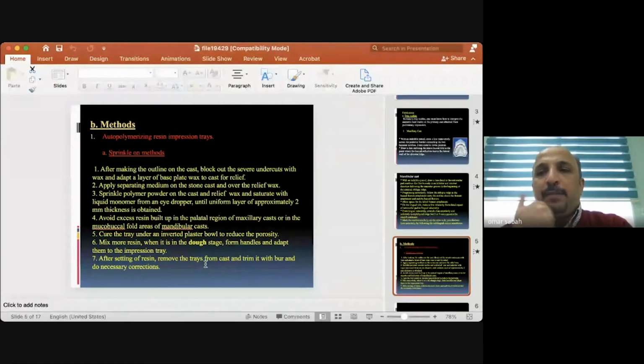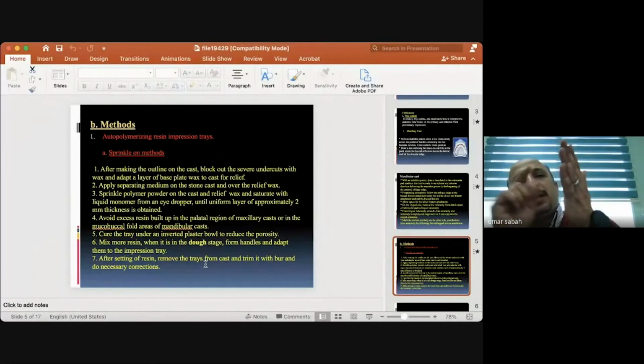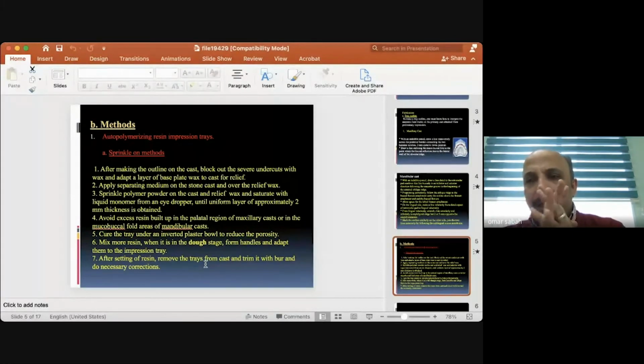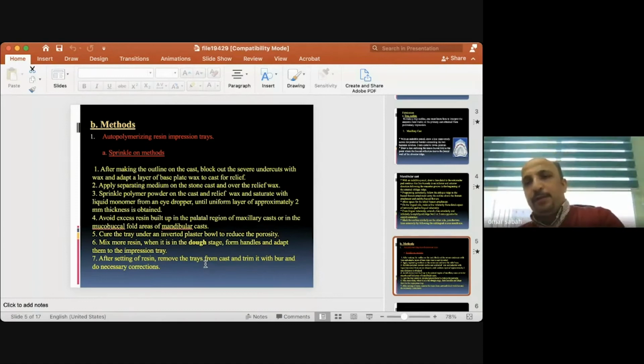The porosity means the air bubbles trapped in your work. So when I remove my cold cure resin, I see some holes, not reached by this material. These are the porosities. Why do they happen normally? Because the ratio of mixing will be changed. Why? Because I normally have a special ratio for the cold cures, and from company to company, sometimes there is a simple difference.